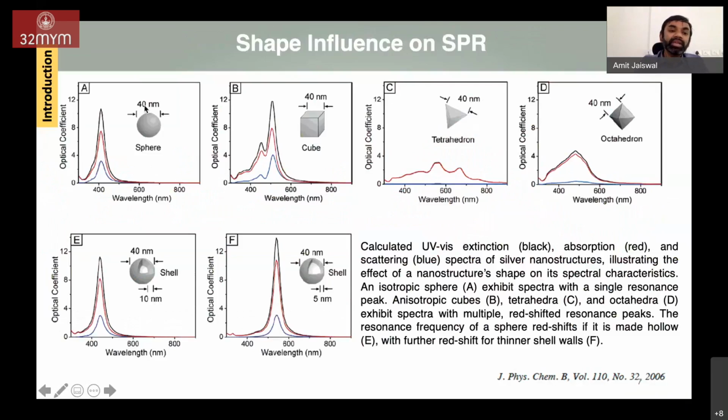If we take spherical nanoparticles and impinge light of suitable frequency, we can get only one kind of polarization because of the symmetric nature of the particle. What we get to see is absorbance happening at a specific wavelength. For example, in the case of silver nanoparticles, we see an absorbance around 410 nanometer, and even if we change the size of the nanostructure, the wavelength at which the surface plasmon resonance occurs changes.